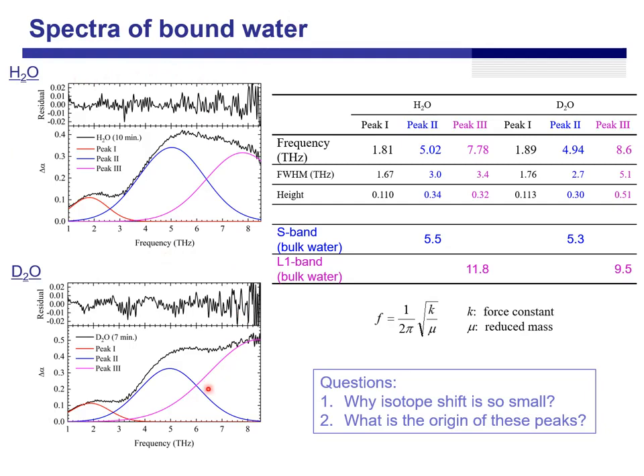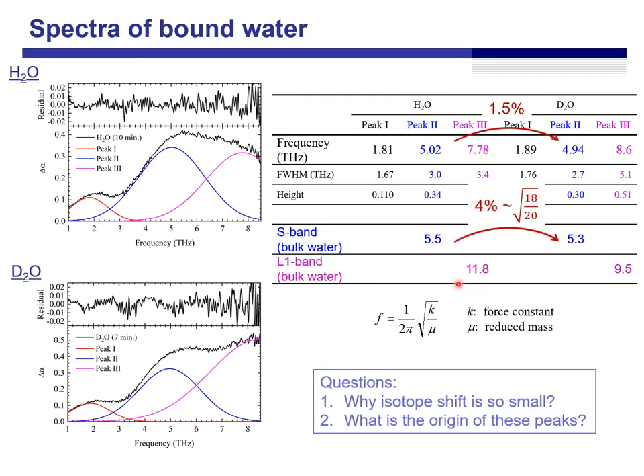So we tried to make an assignment of the bound water. These are the spectra of H2O and D2O. We fitted the spectral pattern with Gaussian functions, and we beautifully fitted the spectra with three Gaussian functions. We named these bands P1, P2, and P3, and this table summarizes the fitting parameters. At first, I assigned these bands by comparing them to the known bands of bulk water: P2 as S-band and P3 as L-band. But something is strange — the isotope shift of the S-band should be 4% due to mass ratio, but it is only 1.5%. And secondly, the frequency of P3 is too low.